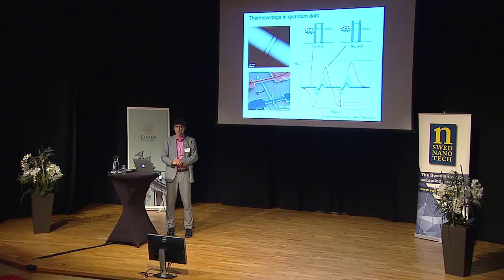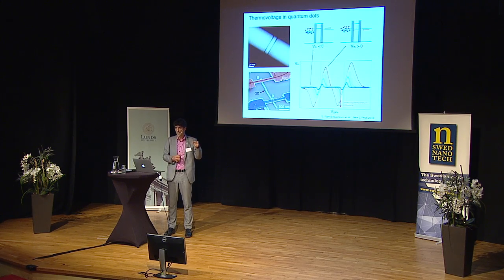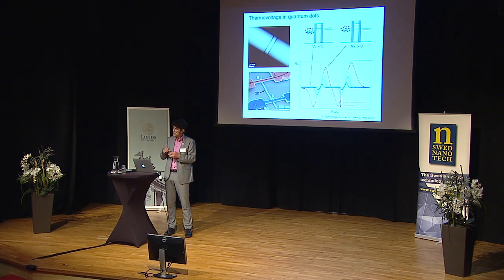To approach this we have been looking at model systems. This is a quantum dot embedded into a nanowire — a very well-defined structure that allows electrons to only exist at very specific, tunable energies, which we can use to pick exactly at which energy we want to conduct electrons. That can be used, for example, by choosing the energy level where you put your electrons, to either have electrons go one way while holes are blocked, or the other way around — so you can even choose the sign at which you want to produce thermoelectric current.